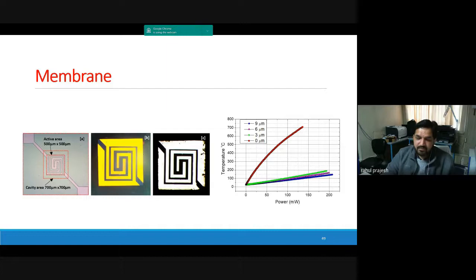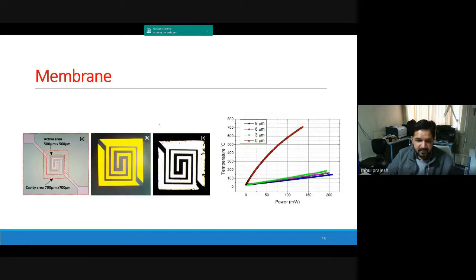Then comes the thickness of that particular membrane from the back. So if you come back to this design again, here is the cavity, and at the bottom of this, you have silicon. Now, should you have silicon at the back or not? That is being considered in this experiment. So you have this design on the top side, and from the back, you see the image. These are transmission images. Light is coming from the back side, and you are looking from the top side. Here you see yellow color, but here you see white color. White color is because you don't have any silicon in the back side, and here you have some silicon. Because of the silicon, you are getting yellow color.